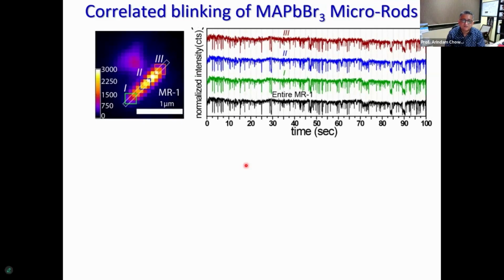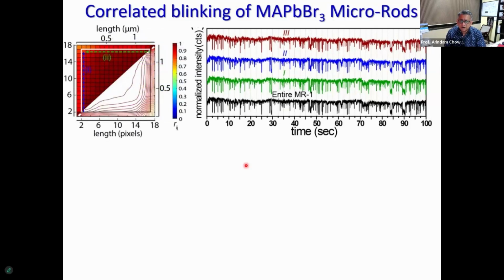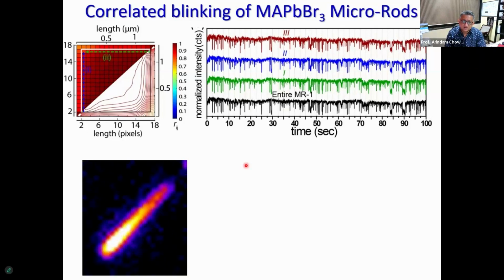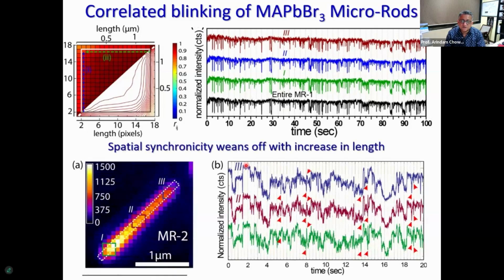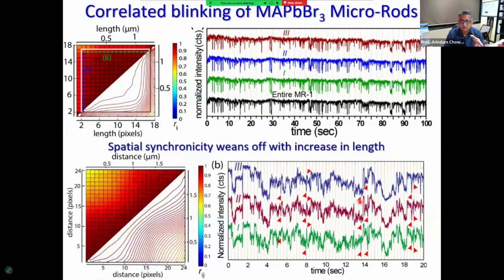This is an example just to show you what correlated blinking rods mean. This is a movie. As you can see in this movie, everything is fluctuating together. If you plot the intensity as a function of time from these 3 places, you will see they are almost nearly identical. The correlation is very high. For longer rods, you start seeing some fluctuations. This is again an isolated rod, which is blinking more vigorously, but here you start seeing some small deviations in the blinking behaviors. There are events where the amplitude of the blinking is low or high, but the blinking events are still temporally correlated. Under these circumstances, you do see a slight decrease in the correlation, but it's still very highly correlated.